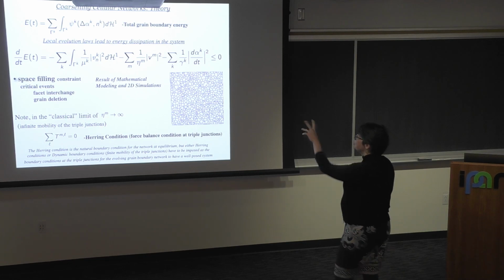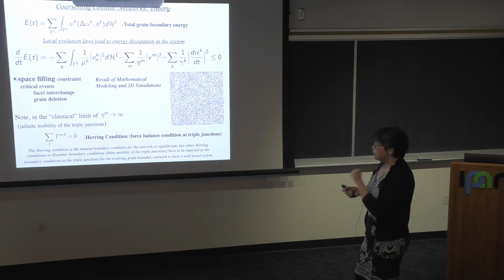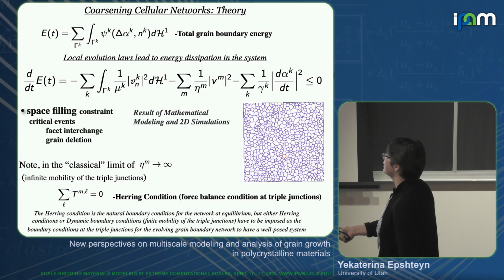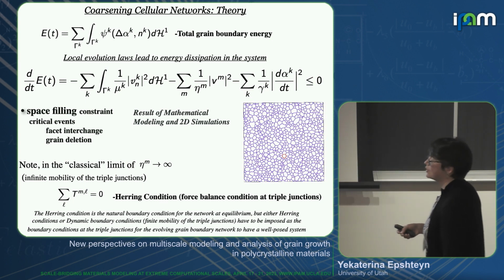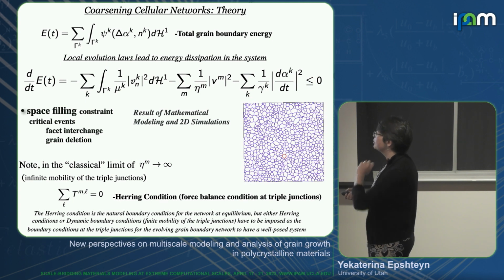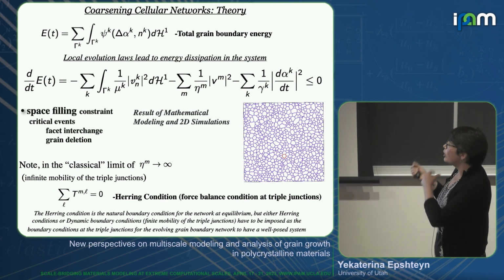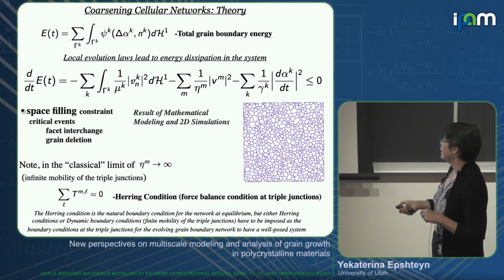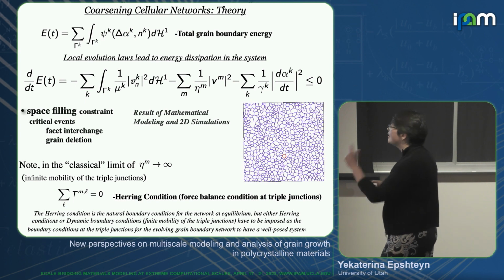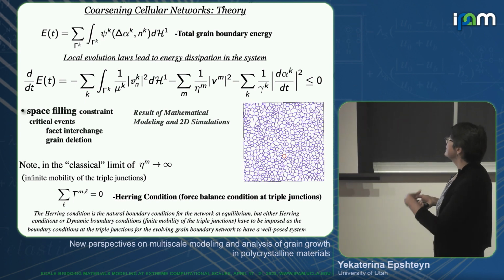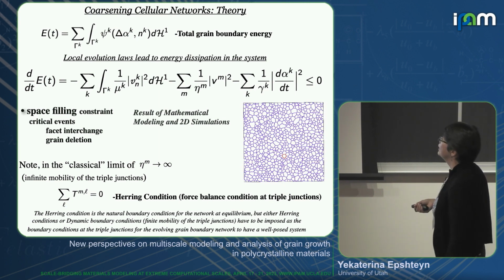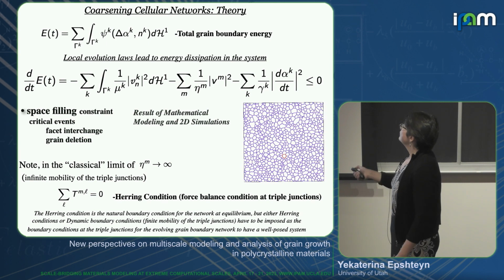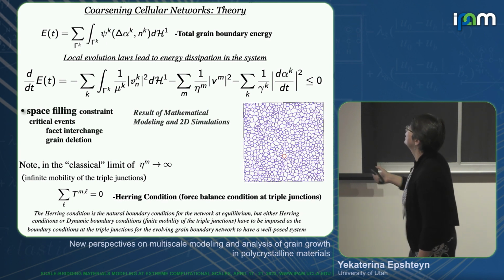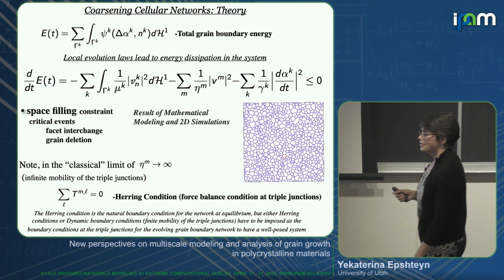So yeah, if you set mobility of triple junction to infinity, you basically eliminate effects of the triple junctions itself, and these boundary conditions, when mobility of triple junction goes to infinity, become force balance conditions, which are natural boundary conditions for the system at equilibrium. But one boundary condition has to be imposed, either force balance conditions, which is a classical choice, or dynamic boundary conditions for the system away from equilibrium, in order to have a well-posed mathematical model. And with the classical assumption that you keep orientations constant, these terms also disappear.